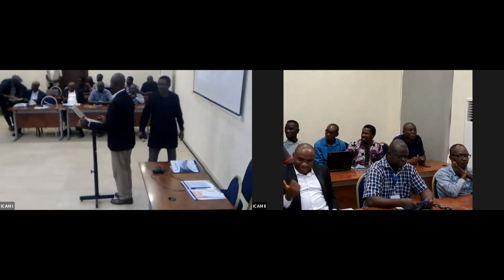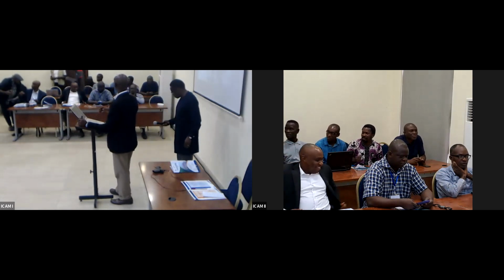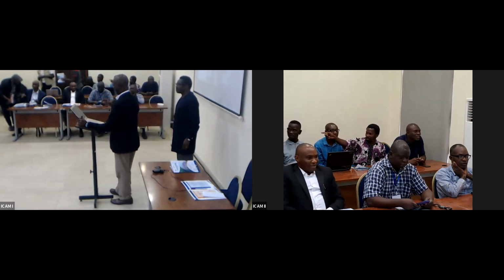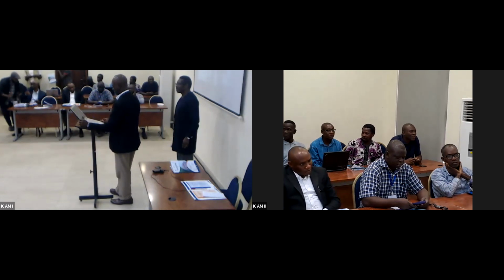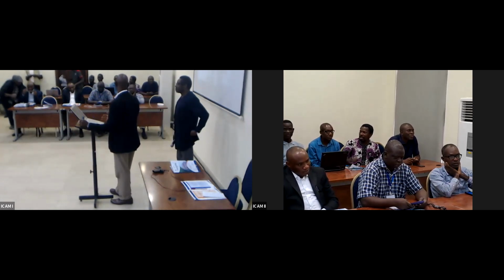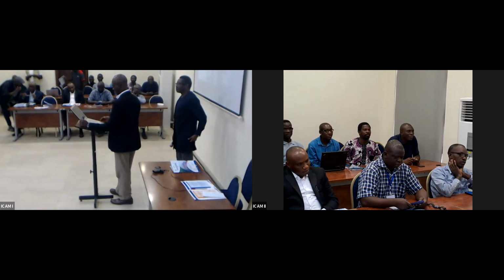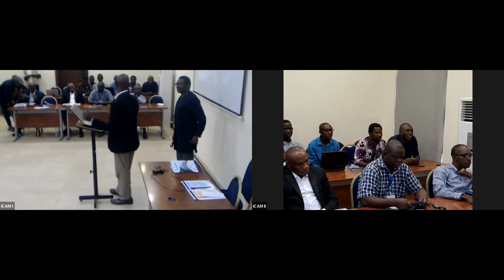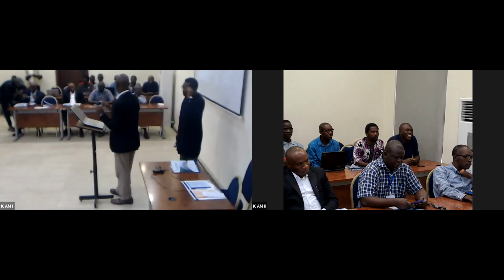Okay. For the experiments, at 11 millimeters, the temperature was 306.9, while for the model, we got 298.5. We have not computed the percentage.